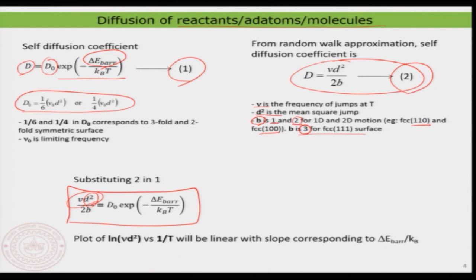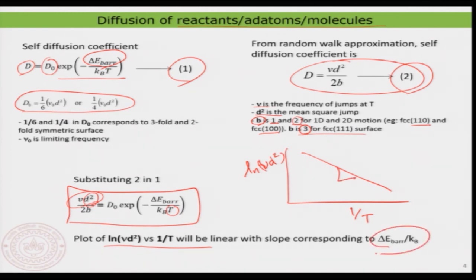If I know these two, I can check this as a function of temperature, and then I can plot log nu d square as a function of 1 by T. What I am going to get is a linear plot, and the slope is directly delta E barrier by kB. So the slope is equal to delta E barrier by kB, and then I can calculate the energy barrier using this.